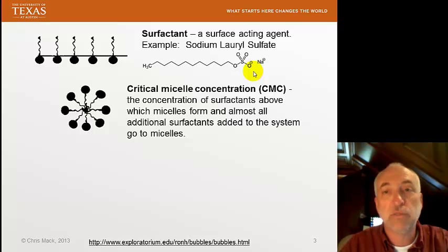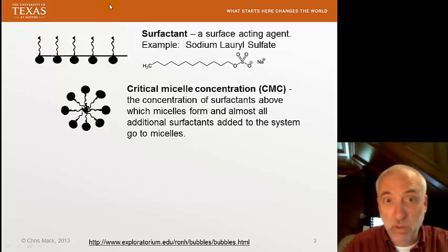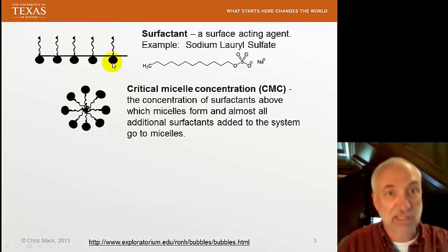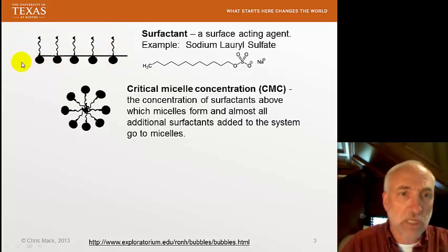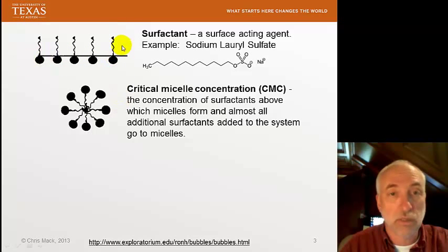These two ends provide the different properties that we need, both for a surfactant and for self-assembly. In this case, one end's polar and the other is non-polar, so if we put it in water, the polar end likes to be in the water, and the non-polar end sticks its tail out of the interface. So surfactants tend to line up at the interface between water and air, or water and other materials. But they can also self-assemble in a different way.